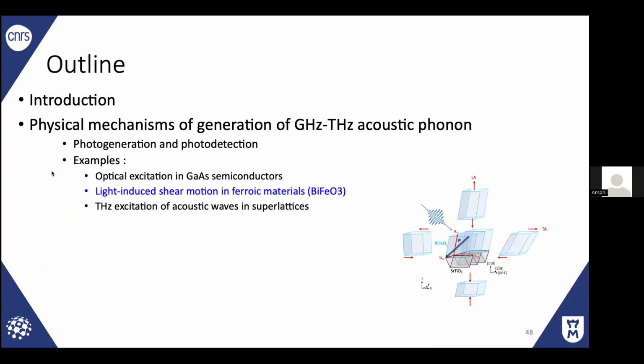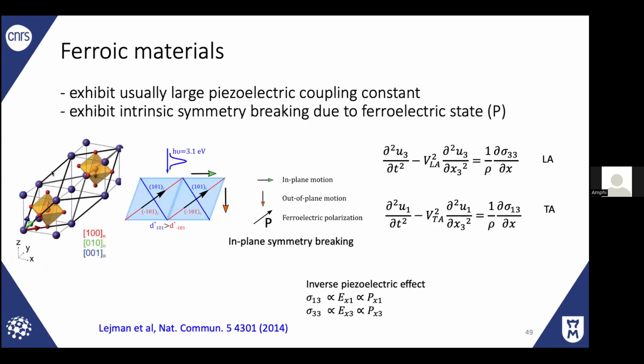So when you play with piezoelectricity, there is something that you think immediately about: ferroelectrics. For ferroelectrics, due to the symmetry, inversion symmetry, in that case, you can induce not only longitudinal, so this is wave equation, but you can induce longitudinal and transverse. You can induce not only longitudinal, but also shear.